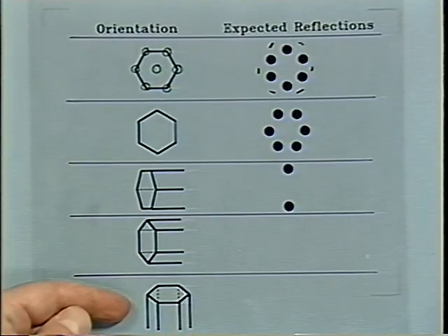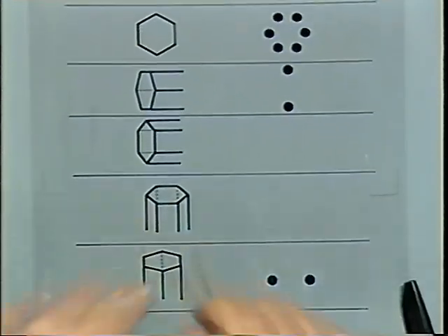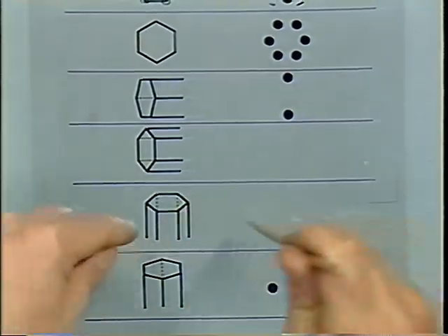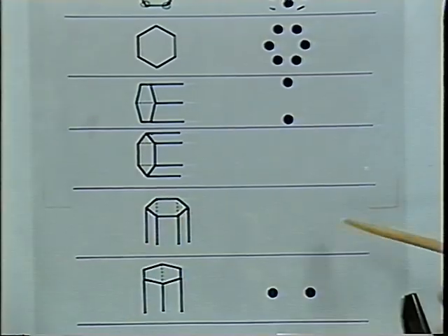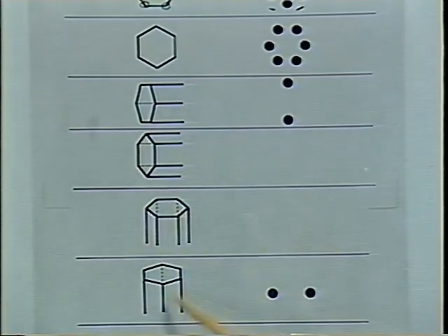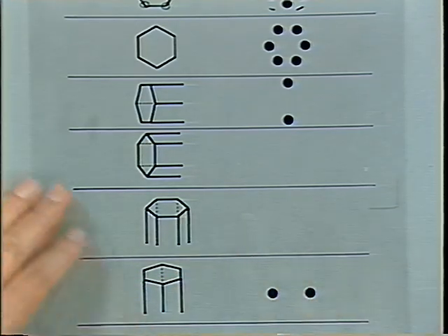Same thing when looking at this structure, a light or the X-ray going on this will not give any innermost reflections. But with this here, again, we will pick up those planes, and you will see those reflections. So small angle X-ray gives us an interesting tool to look at the order in the entire sample. We pick up the order from the whole volume, from a larger control volume in that sample.